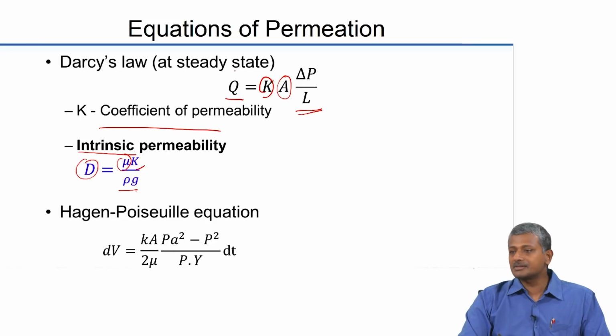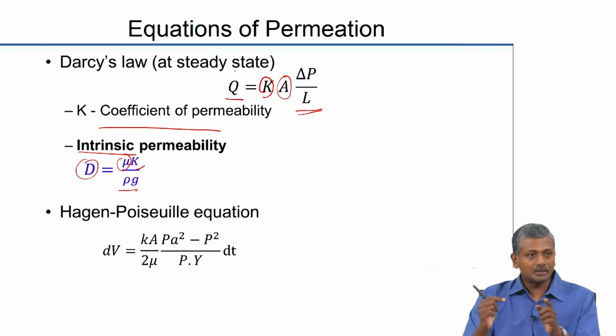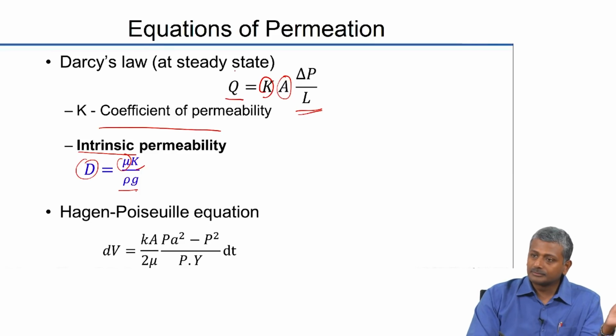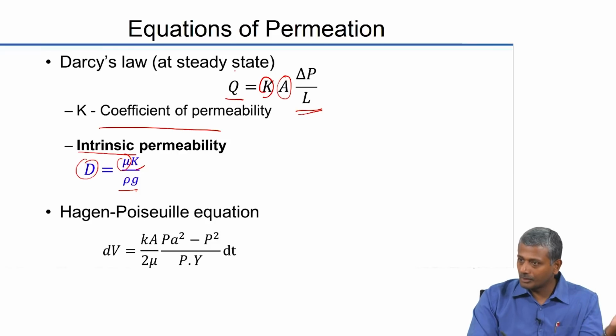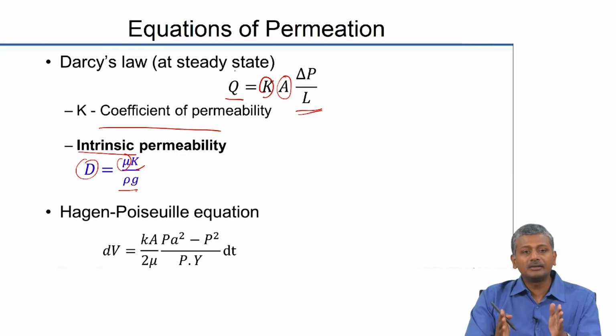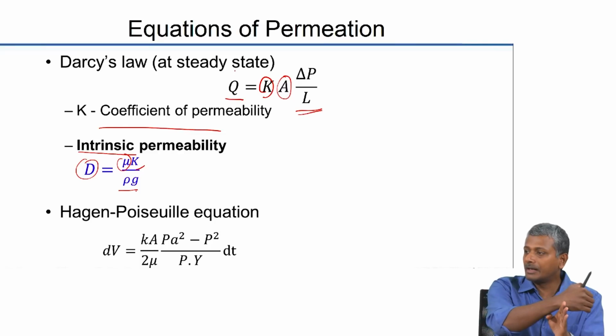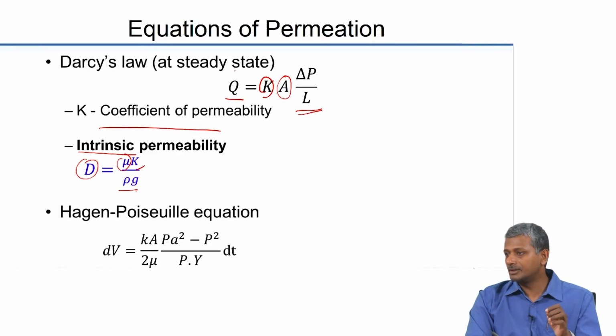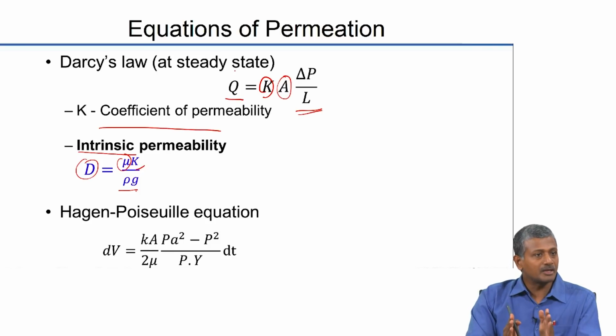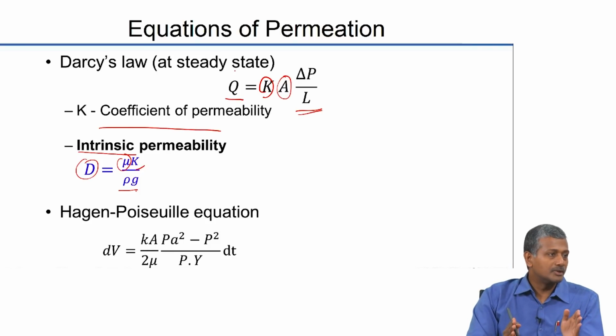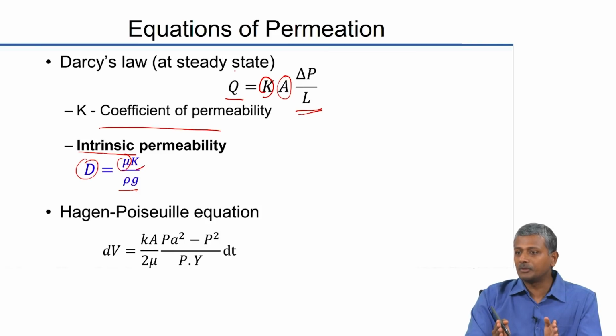The only difficulty is that setting up this kind of an investigation for concrete can be quite difficult, because now you're talking about subjecting a concrete to water pressure on one side and then making this water come out on the other side. Water has to actually flow out of the concrete, and you need to wait until the rate of flow at the downstream end is constant to get the steady state condition. So imagine it will take you a long time for that to be achieved.